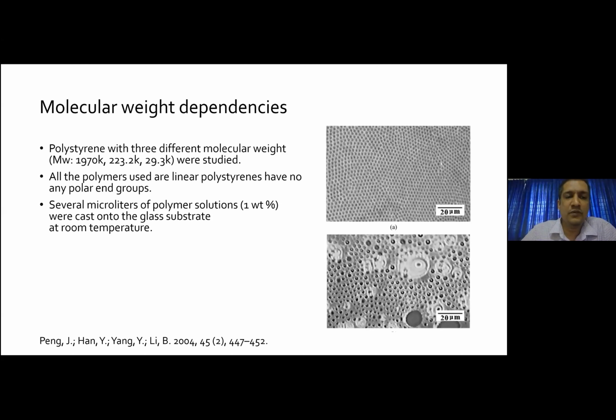Now coming to the next point, most often the belief till date is that if you have polar end groups, that will facilitate the formation of the breath figure, and if there is absence of any polar groups, it is very difficult to get breath figure formation. But this particular group deliberately avoided the use of polar end groups, and they said that the viscosity of the medium, the viscosity of the chloroform solution, is more important than the end groups. That's what they demonstrated by varying the molecular weight alone, and they did it with several concentrations, and even with very high concentration of the polymer, they found the pattern formation is not uniform, and the pore size becomes very small, and multimodal distributions came, and so on.